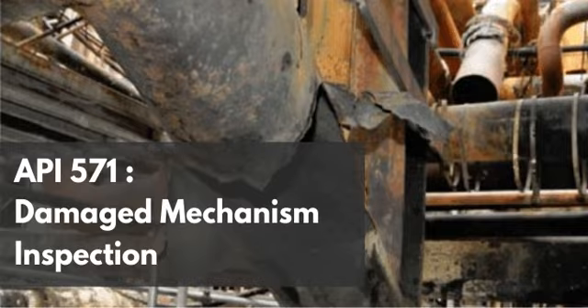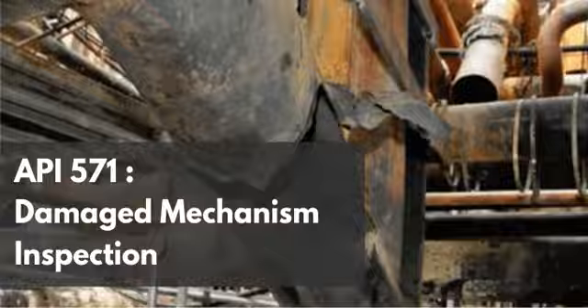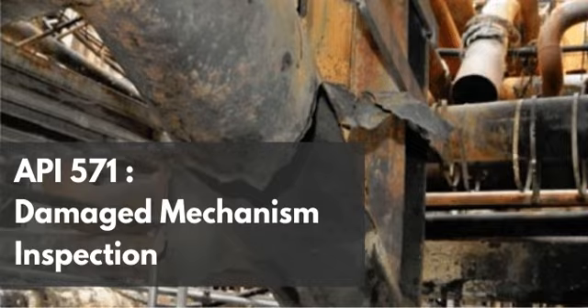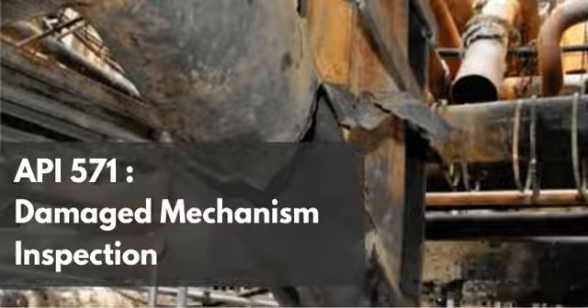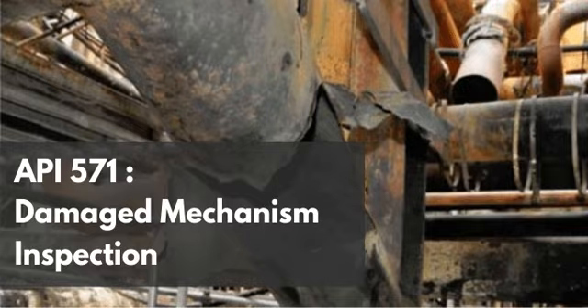Wait, so the chromium shield is basically neutralized, it just doesn't work? In this specific chemical environment, yes, the shield fails completely. The specific corrosive mechanisms of hot lean amine combined with the heavy presence of CO₂ completely overpower the standard protections that we assume these ferritic structures have. Wow. Yeah, the chemical breakdown of the amine into those organic acids and heat-stable salts creates an environment that relentlessly attacks the body-centered cubic iron matrix. It just doesn't matter whether there is 1% or 5% or 9% chromium present.